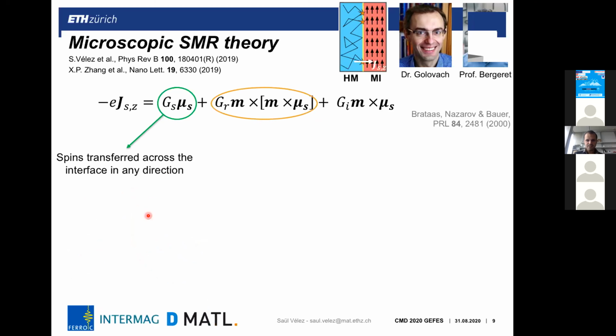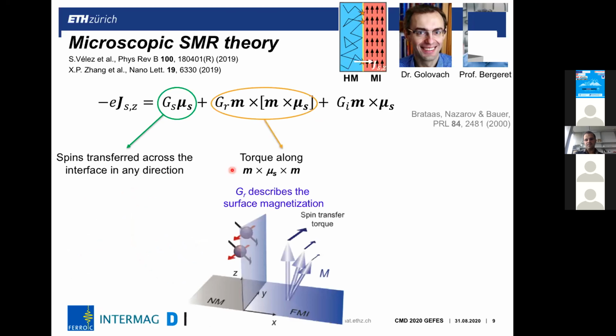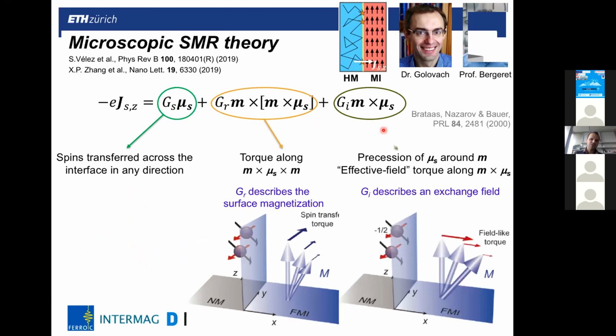So the second term, because of the symmetry, would be equivalent to the damping-like torque on the magnetic insulator. And the third term is the field-like torque. In most systems, this part was neglected initially in the spin Hall magnetoresistance theory, and in most systems it was found that the real part of the spin mixing conductance was dominating over the field-like, but it was not addressed why this could be in a device.